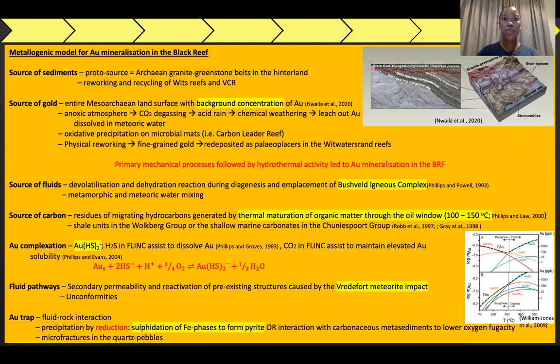Based on Le Chatelier's principle, the precipitation of gold in this equation will be caused by the decrease in hydrogen sulfide species and the decrease in oxygen fugacity or an increase in pH. The reaction of gold-bearing fluids with iron-bearing minerals depleted the sulfide in solution by forming pyrite or pyrrhotite and decreased the gold solubility. The interaction of fluids with carbonaceous metasediments also lowers the oxygen fugacity. This accounts for all the native gold found in close proximity to pyrites and irregular-shaped carbon nodules. This shows that the main precipitation mechanism in the Black Reef is precipitation by reduction.